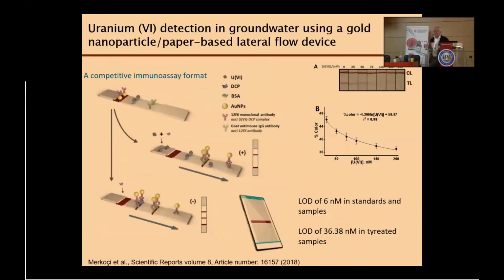And we extended this even to detection of uranium. Again, we prepared this in collaboration with Florida. And we sent these devices to our partner in Florida and applied this to detect the uranium in underground water that was contaminated with uranium, as an alternative to radioimmunoassay that needs professional people and also is more expensive. And they did the detection by using a smartphone, capturing the image and then measuring, detecting really very low levels of uranium in water.